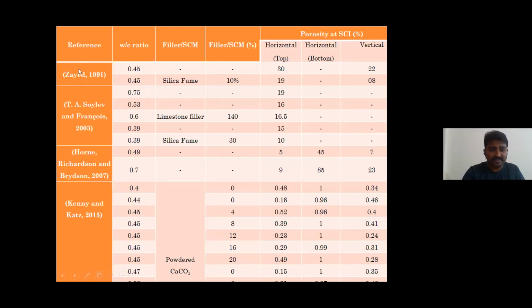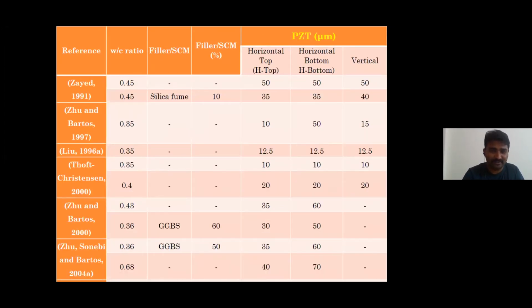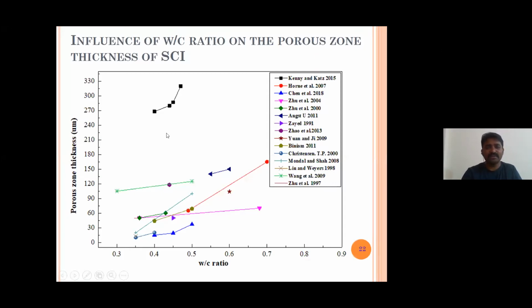So these are references, Zayed and others: water cement ratio, filler, and the porous zone thickness. These are some of the literature data. Some people have used silica fume. What will happen if I add silica fume? All of that people have studied. And these are a few others, in terms of micrometers. To make that research in a condensed form, these are different researchers that have studied the effect of water cement ratio. Please remember, this is literature data. We have just compiled the literature data. These are not the data that I have produced.